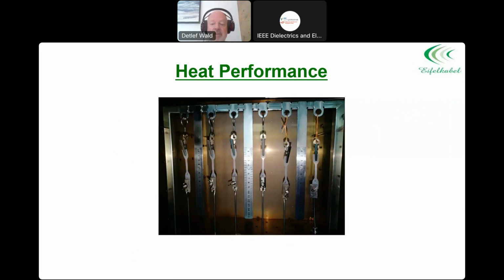What we also did, and now you might be surprised, this looks like a hot set test. This is a test that we have done and presented some years ago at Jicable in a session in Paris. That was before Corona, so that's the new time counting. And we compared polypropylene with XLPE. We didn't go for the normal test. Heat elongation is done at 200 degrees, 15 minutes. So we did it at 135 degrees and a longer time, 42 days. And the elongation of polypropylene and XLPE were in the same range over time. And the surprising thing, surprising even for me, was that the polypropylene even moved back when we removed the weight. So the elongation was not permanent. Why? I still don't understand.